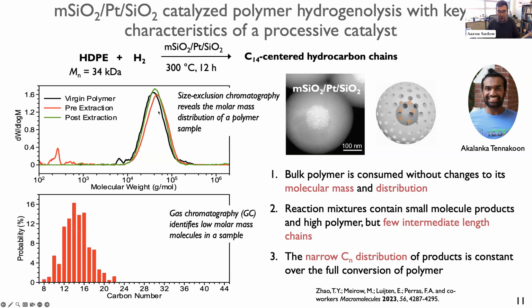And what you see is the molecular weight doesn't change. So over this conversion, what we're doing is we're eating up some select portion of these, but the molecular weights of the chains don't change. We convert some and leave the rest behind basically unreacted. And what's converted is made into this low molecular weight distribution, which we extract and analyze by GC.